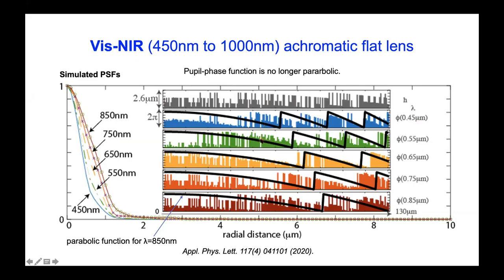Clearly, every phase distribution at each wavelength is different, and each of them are different from their corresponding parabolic phase distributions as well. But if you take each of these phase distributions and allow this phase to propagate into the focal plane, which in this example was, I forget the exact number, but a few millimeters away, you end up with tightly focused point spread functions.